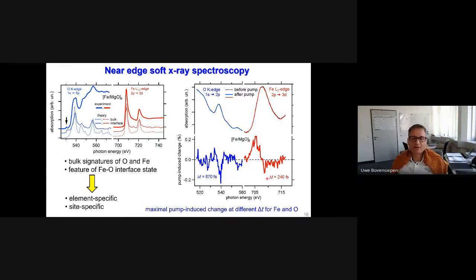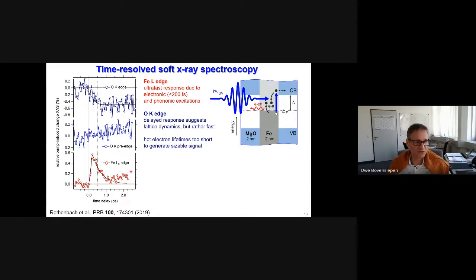So we proceeded now with the experiment and identified 3 different regions of interest in the photon energy, where we now do a specific time dependence. And this is shown here at this slide. So here you see the time dependence at the iron L3 edge, at the oxygen K edge, and the oxygen K pre-edge region. And without further discussing, at a first glance, you see that within these first 2 picoseconds, the response is completely different. So we probe different processes at these 3 edges. And this highlights that you can really learn a lot if you do this soft X-ray pump probe spectroscopy.